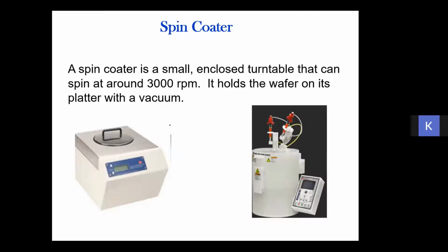How much resist thickness you need, you have to calibrate first by using various resist concentrations in a solvent, and then using various speeds of the spin coater, and find out the thickness of the spin-coated resist over the silicon by a process like ellipsometry and so on. So after you know that resist thickness, you can fix your speed and always use that speed from then onwards.